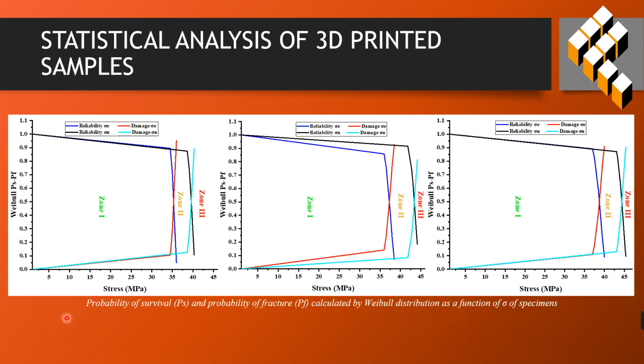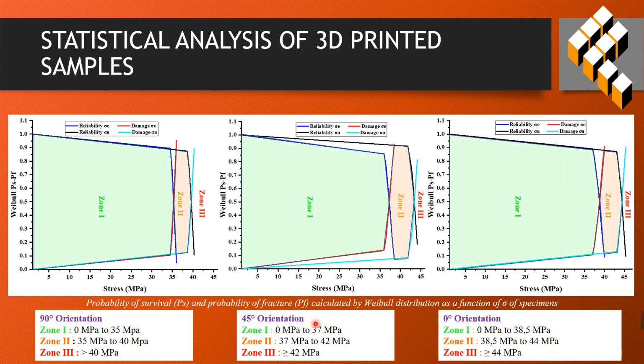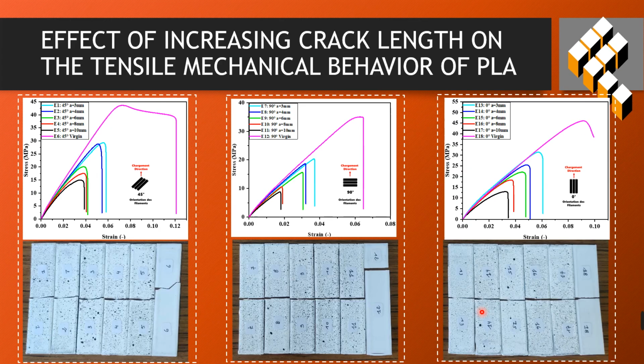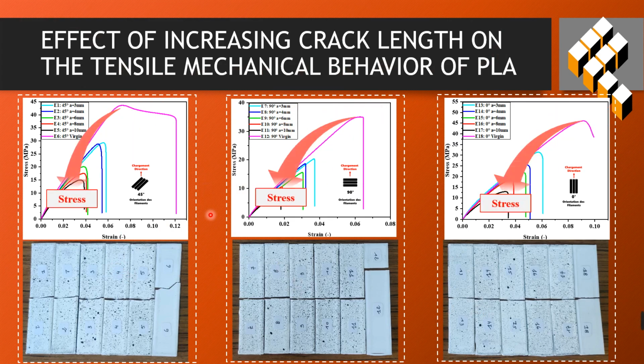Also, we note that the mechanical behavior of the material depends on its orientation relative to the direction of the applied load, with zone shifts indicating better performance at 0 degrees. A second series of tensile tests was conducted on 80 samples, with 6 samples for each orientation and with various initial cracks from 3 to 10 mm. The curves show a significant decrease in the residual ultimate stress as crack length increases, and also that samples at 0 degrees are the most resistant, while those at 90 degrees are the most damaged.